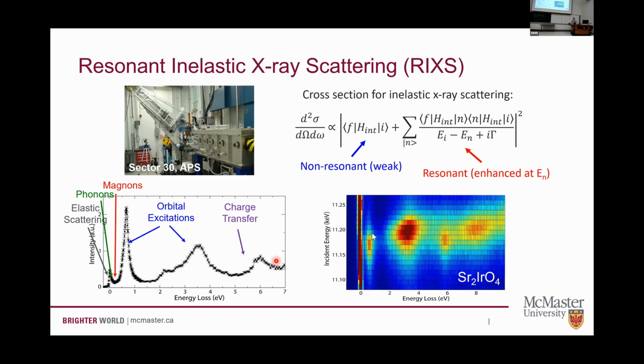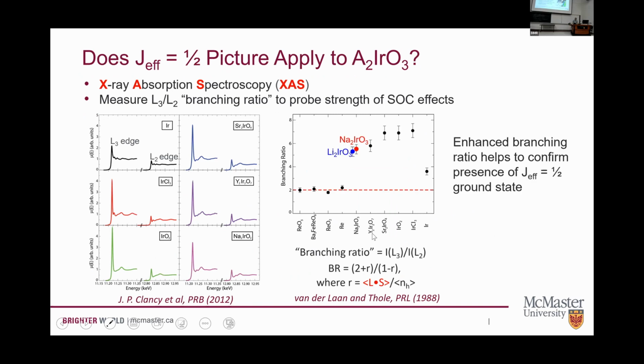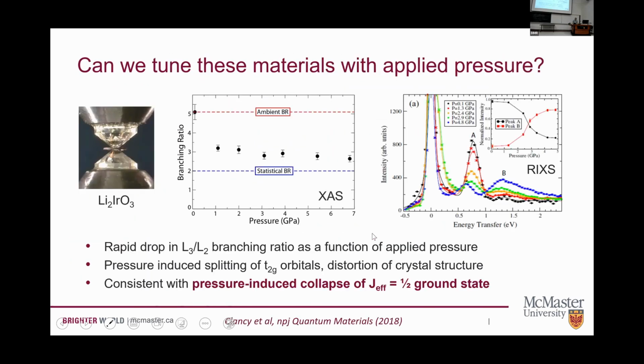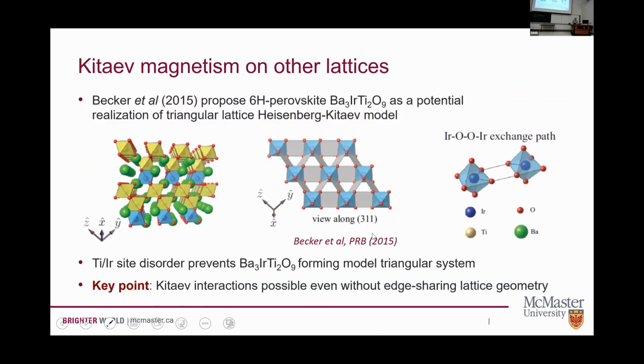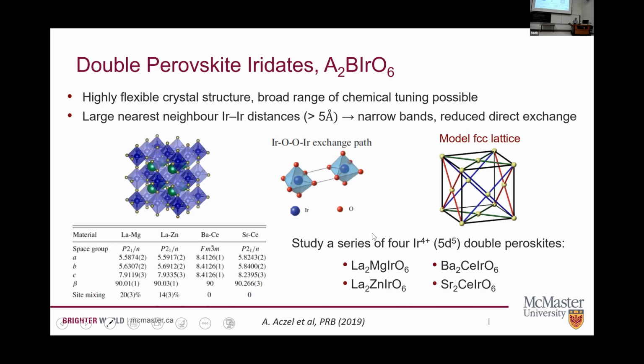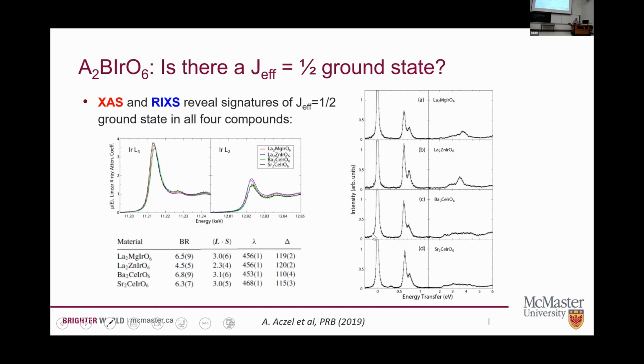We should talk about them coming for an electron diffraction. You were looking at some double perovskites, right? They're cubic, and of course in the cubic case everything would have to be exactly 90 degrees, but that's not the case for the monoclinic one. But you didn't see any differences? Yeah, it's quite surprising. Because we had expected that this would be almost like a fruit fly experiment where we could look at the effect of these small changes in local structure on the RIXS spectra. But the difference in this non-cubic crystal field splitting is very small and almost unchanged.